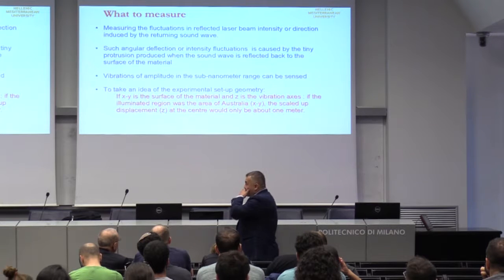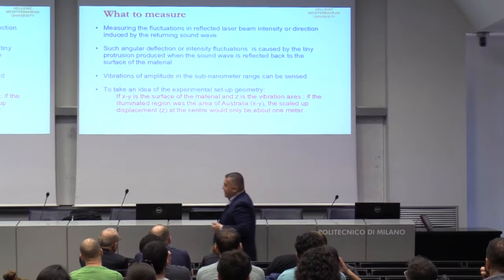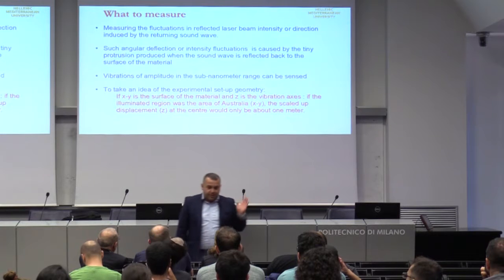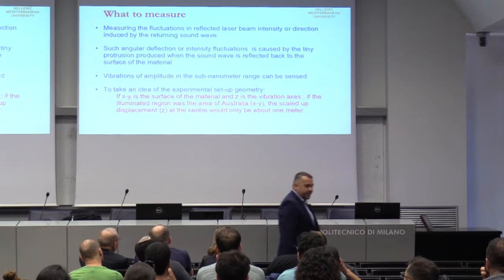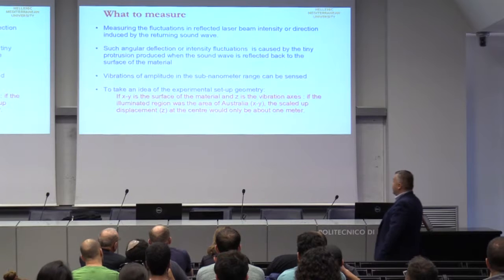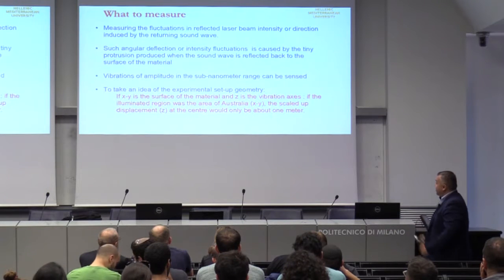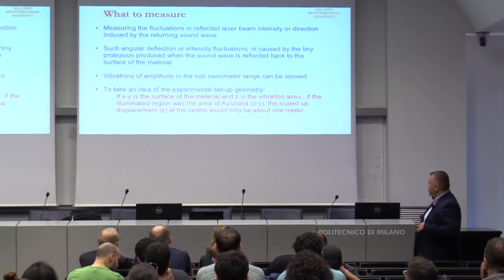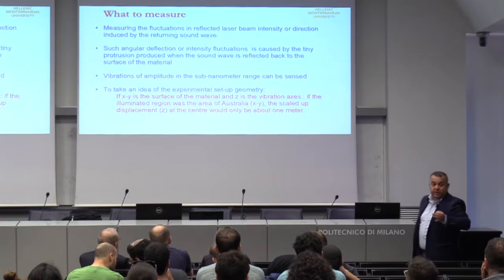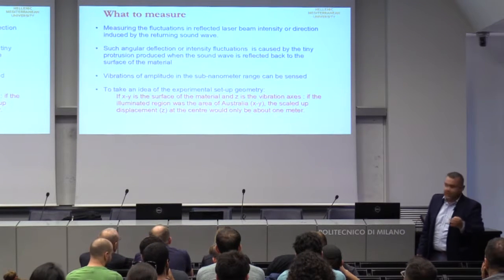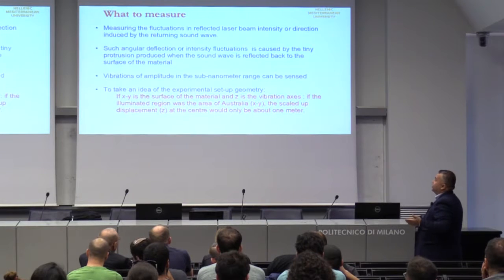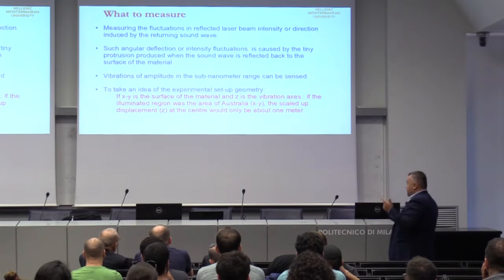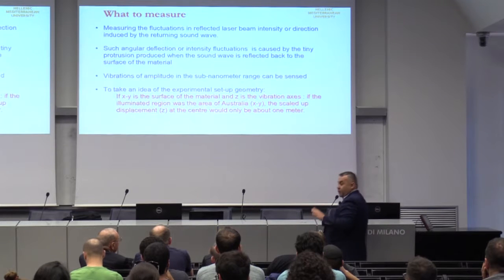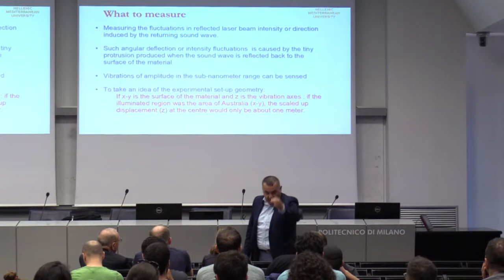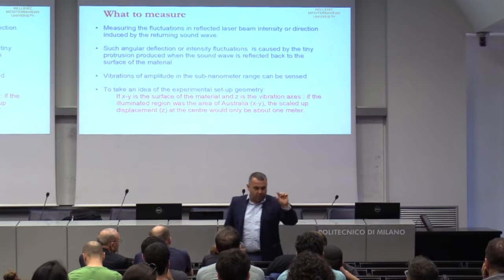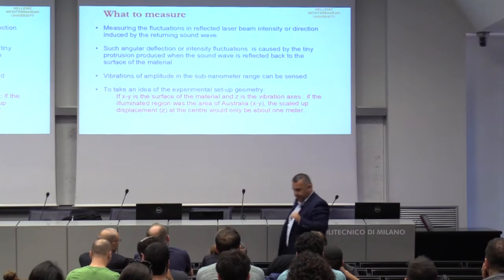Vibration of amplitude. So to get an idea of an experimental setup geometry of this kind of thing, you can read this red sentence that I wrote here. When we have an XY surface of the material and Z is the vibration axis, if the illumination region, which is on the order of 10 microns, 20 microns, was the area of Australia, for example, the scaled-up displacement at the center would be only 1 meter. So we illuminate Australia and we try to observe 1 meter of vibration.